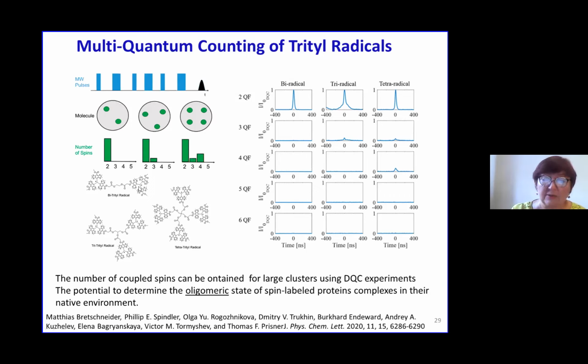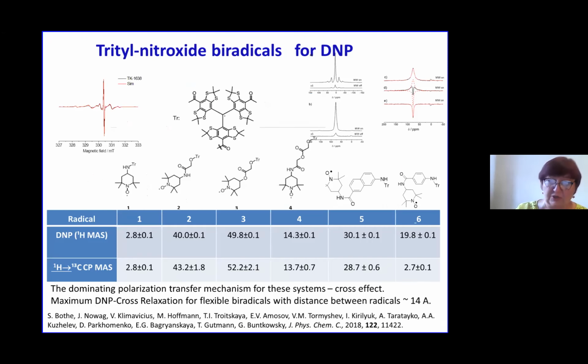Then model compounds like bitrityl, tritrityl, and tetratrityl radicals were synthesized. You see here that for the biradical we have only 2 quantum coherence, for the triradical 2 and 3, and for the tetraradical we have all these 3 lines. Unfortunately, the technique is very demanding, the phase should be very precise and so on. Despite it being X-band, we really can't do it in our place. So this work is continued because we would like to apply this technique for biological objects.